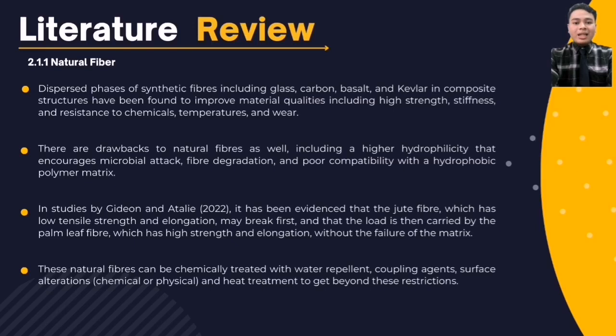In study by Gideon and Atalie 2022, it has been evidenced that the jute fiber, which has low tensile strength and elongation, may break first, and that the load is then carried by the palm leaf fiber, which has high strength and elongation, without the failure of the matrix. This better stress transfer from matrix to fibers leads to an increase in the mechanical properties of the hybrid composite. Another factor is that palm leaf fibers' high cellulose content also helps to improve the mechanical qualities of the composite. Additionally, the decrease in tensile strength is brought on by an unfavorable level of compatibility between the matrix and lignin in the interfacial region. Lignin decreases the bending mechanical characteristic of the composite material.